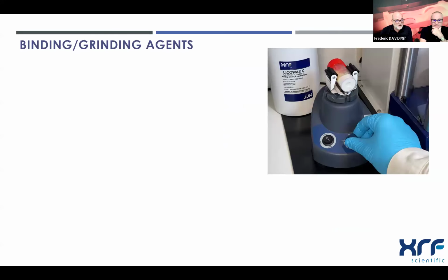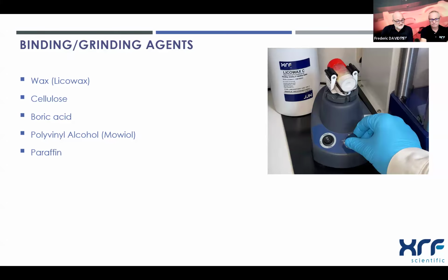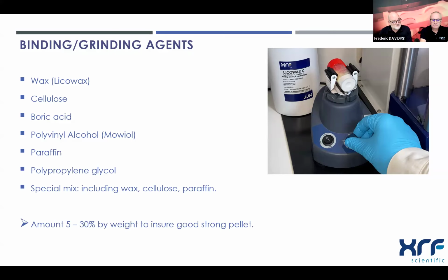So now, the most used binders and grinding agents are the wax, the Licowax. This is probably the most used one. Cellulose, boric acid, polyvinyl alcohol, paraffin, polypropylene glycol, and some special mixes including wax, cellulose, paraffin, depending. And generally the amount is between 5 and 30% by weight to obtain good and strong pellets.